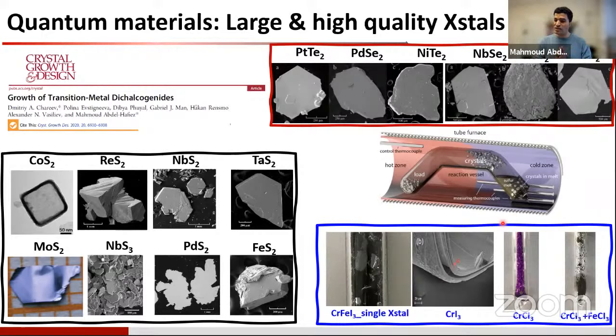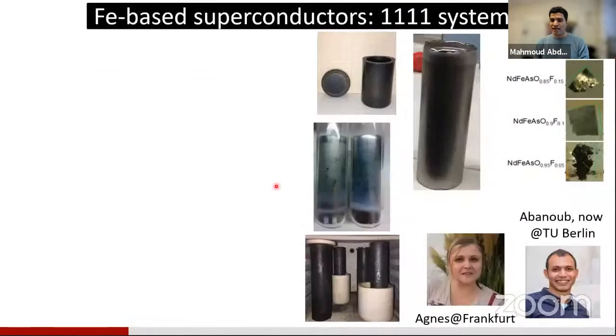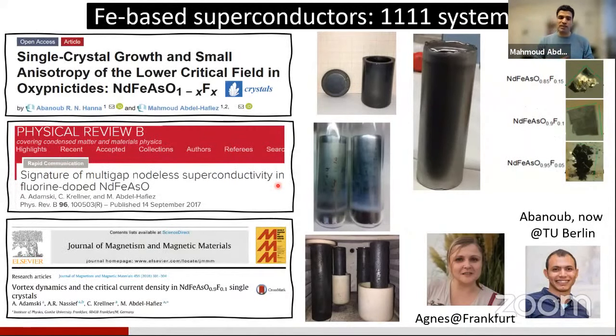Using evaporation techniques, one can get very large single crystals. And you can study a lot of things on this material, because of the high quality and the shininess of the surface. You can also see the layered structure. Even with tweezers, you can cleave the materials to have a very shiny surface. Also, there is what we call the flux technique, which is very important particularly for iron-based materials to achieve high quality single crystals. And single crystals are very important to understand the physics or the chemistry of the materials which we are working on. All the crystal growth has already been published in several places, and you can also contact us for further information, and also if you need any kind of materials or effort in these directions.